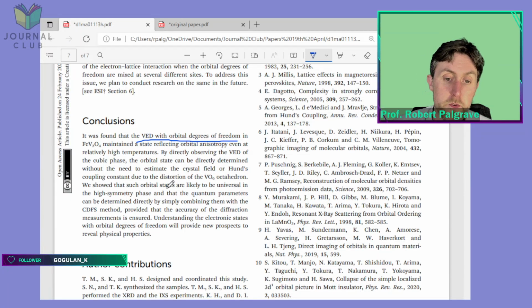We show that such orbital states are likely to be universal in the high symmetry phase, and that the quantum parameters can be determined directly by simply combining them in a CDFS model, provided that the accuracy of the diffraction measurements is ensured. Understanding the electronic states with orbital degrees of freedom will provide new prospects to reveal physical properties. I think the last sentence there is fully justified.